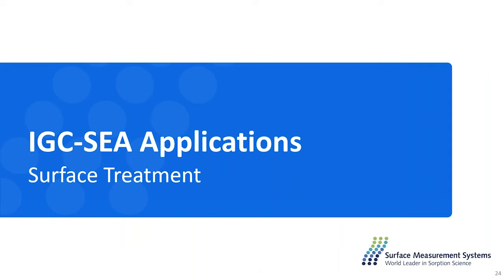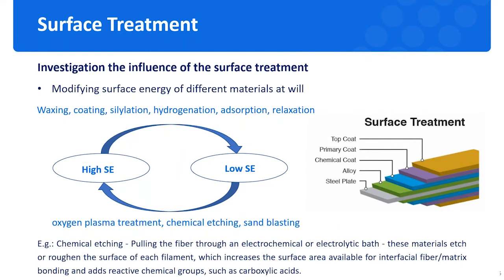And then we can focus on the applications of the IGC technique. So normally we will do some kind of surface treatment on our material to change the surface energy for a more desirable product. In order to lower the surface energy, we can physically cover a surface by waxing or coating, or we can introduce some uniform functionalization by silanization or hydrogenation. Or we can also increase the surface energy by introducing a high energy functional group through chemical treatment or oxidization, or by sanding or chemical etching.